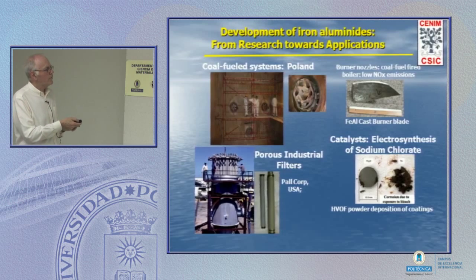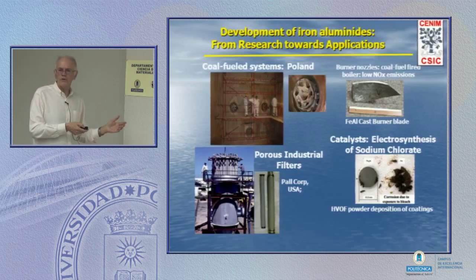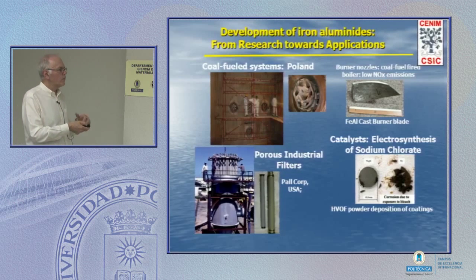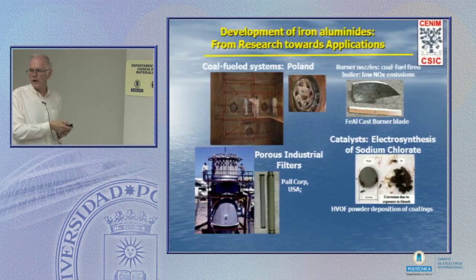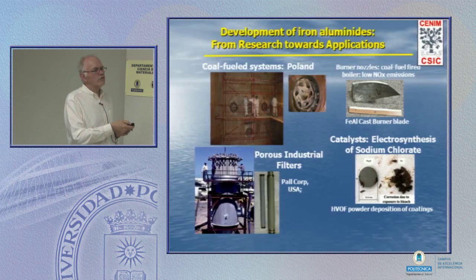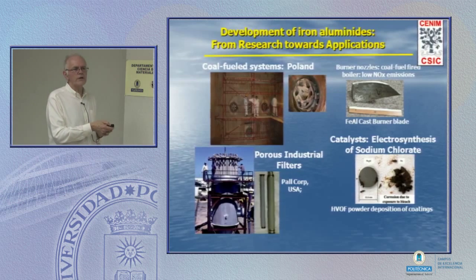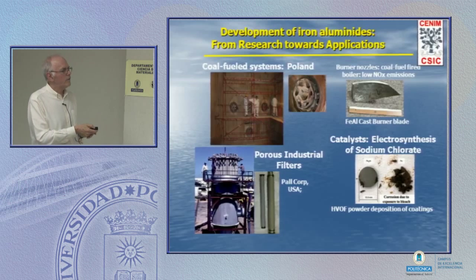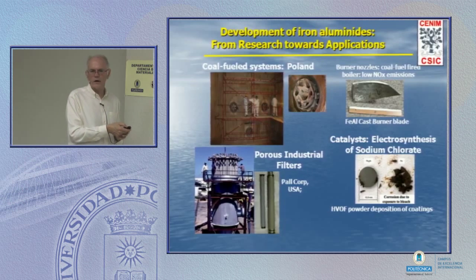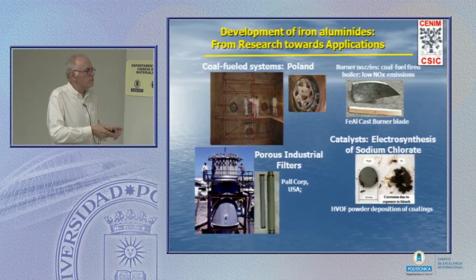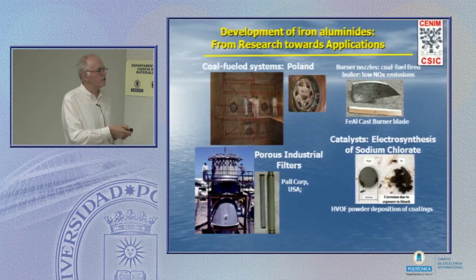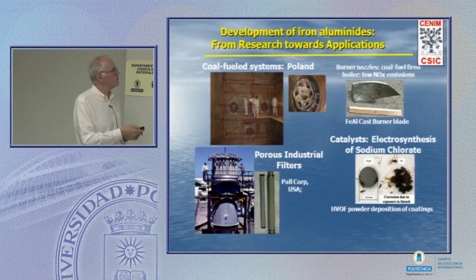Here's a second example. This is an industrial filter. We're filtering out, I don't know, carbon particles, maybe oxide particles from within some dirty industrial, very hot gas. Here's a filter element, which is made of iron aluminide. Again, a couple of humans to give you some idea of the scale. There's something like 100 or so of these fuel elements here in this filter. Catalysis, electrosynthesis of, this is bleach. Tons of bleach are used per ton of paper pulp, wood pulp to make white paper. This is an enormously difficult oxidizing environment. If you make your container out of iron or steel, this is what happens. Make it out of iron aluminide, and this is what happens.